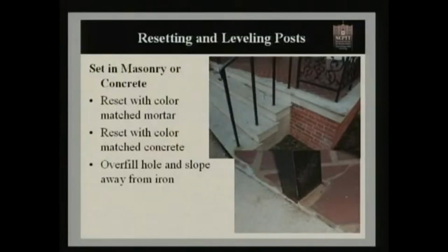Now also, your fence posts and panels may be set in masonry. So this is really important. If it's set in masonry or concrete, you'll want to get a color match mortar. And if it's historic material, you're going to want a lime mortar. If it's a concrete, you're going to want to try to match that concrete in color and in strength. And you want to overfill that hole and slope it away from the iron.